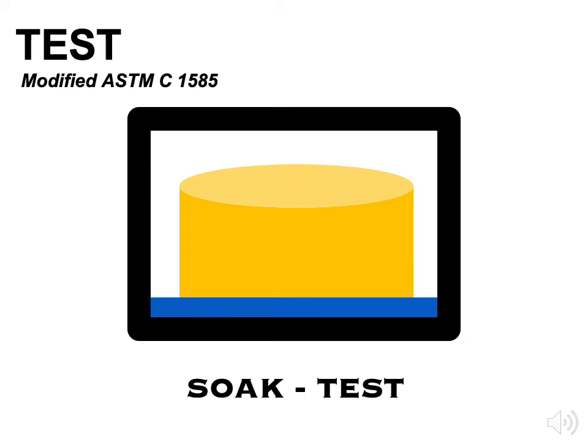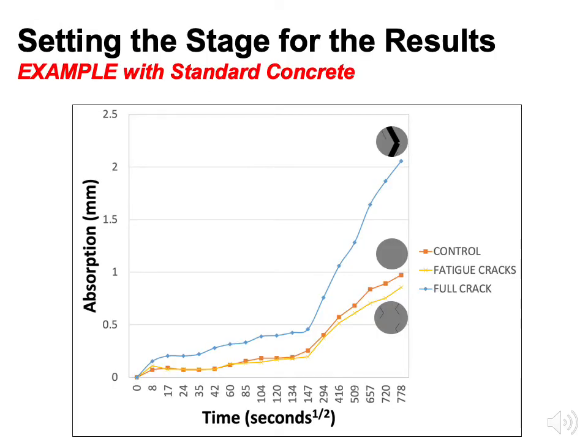Now, the first day is probably the most exhaustive day with testing, where you're testing it, I think, 1 second, 2 second, it goes in these multiples until you get to about 6 hours, and then you start going a little bit longer intervals. And what we've done here is we've set up an example with standard concrete where we have a control concrete with no cracks to it. Then we have, in orange, a concrete sample with fatigue cracks in it. That's taking our concrete sample, instead of cutting it right down the middle to create that manufactured 1/32 of an inch crack, we're applying 40% of the load that would cause catastrophic failure, on a cycle of 10 times to create those microscopic cracks. And then, of course, finally, we have that manufactured crack at 1/32 of an inch.